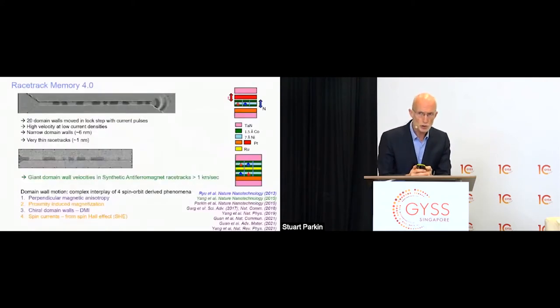And this just shows you some images of racetracks in the laboratory. Now, these racetracks are too wide to be technologically useful. They're 2 microns wide. These are 50 microns long. But we can image them optically. The optical resolution is about 0.6 microns. Nevertheless, by applying current pulses, we can image the structure of 20 domain walls, apply a current pulse, and we can see them move synchronously backwards and forwards. In this case, in a single racetrack at speeds of 300 meters per second.